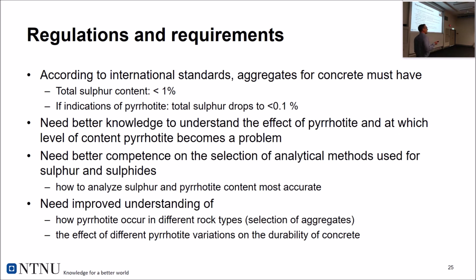And the regulations, these are real European standards, say that total sulfur content in aggregates for concrete cannot be higher than 1%. If you have indications of pyrrhotite, this limit drops to 0.1%, and they don't say more about what's an indication of pyrrhotite. It's just an indication. So if somebody looked into a microscope and said, okay, I saw one grain of pyrrhotite, then this is the